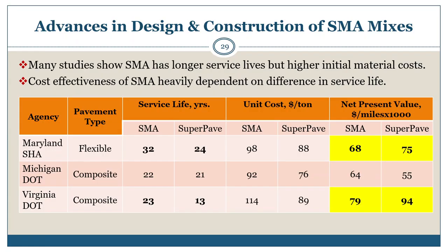This slide, as noted previously, includes information from the previous slide, but in an expanded version. Many agencies, not just those listed here, show SMA has longer service lives but higher initial material cost. The cost effectiveness of SMA is heavily dependent on that difference in the service life itself between SMA and Superpave or conventional dense graded mixtures. Maryland and Virginia have reported SMA to be cost effective, while Michigan has not found SMA to be cost effective in comparison to conventional dense graded mixes. The reason for that finding or observation comes back to the difference in service life.